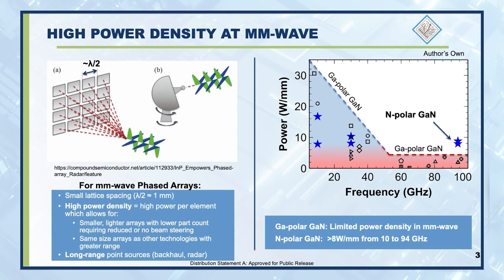The biggest advantage of nitrogen polar gallium nitride is the availability of high power density at millimeter wave frequencies. If you take a typical millimeter wave source, it's made up of an array of elements as shown here, and each element produces power, and by arranging the amount of power that is coming out from various elements, you can direct the beam or increase the power or both. At millimeter wave frequencies, the spacing between these elements is typically determined by the wavelength, and that wavelength is small, about 1 millimeter. So you don't have much room to put in a microwave element to produce the power. Hence, if you want a lot of power from a small area, you need high power density.